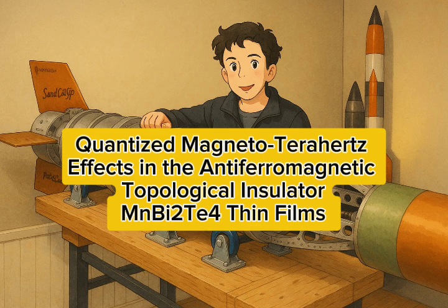Sure. Think of polarized light like a wave shaking in just one direction, say, up and down. When this light goes through a magnetic material, like MBT in a magnetic field, that direction of shaking can get twisted. The amount of twist is the Faraday rotation. Okay, twist going through. And Kerr. Kerr rotation is the same idea, but for light that reflects off the surface. The twist happens upon reflection. Got it. So measuring both gives you information about transmission and reflection. Exactly. It provides a really comprehensive picture of the magneto-optical response. You'll learn how the material interacts with light under magnetism, both on the surface and slightly deeper.